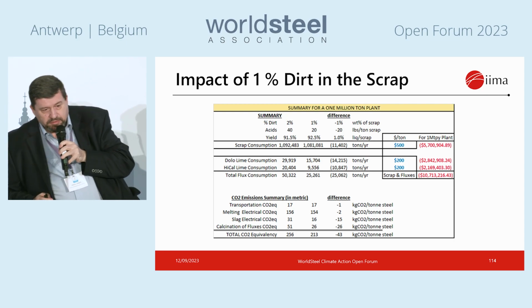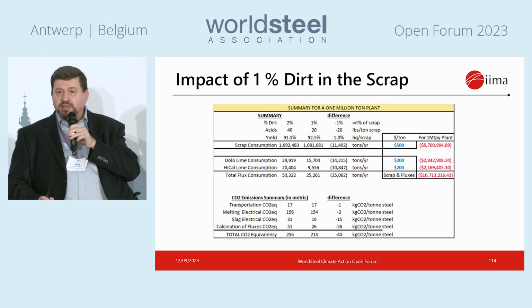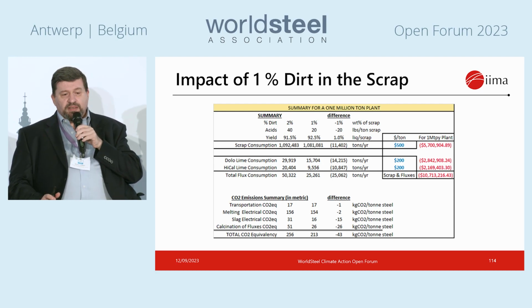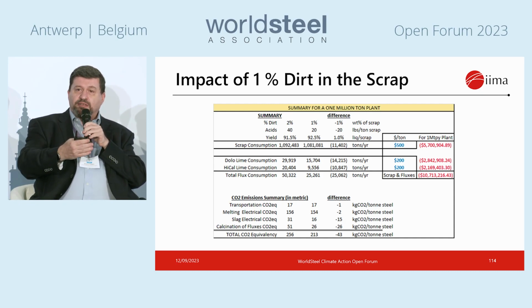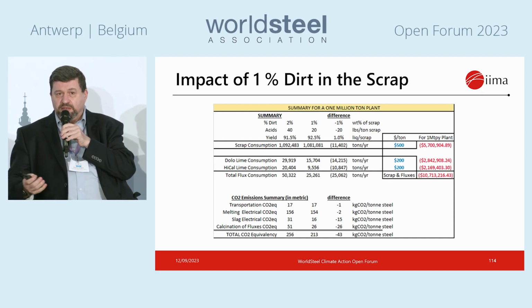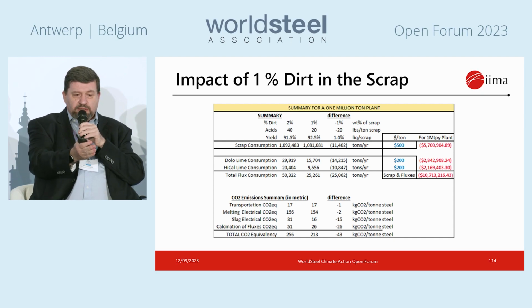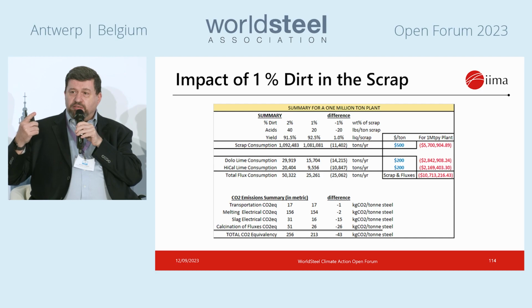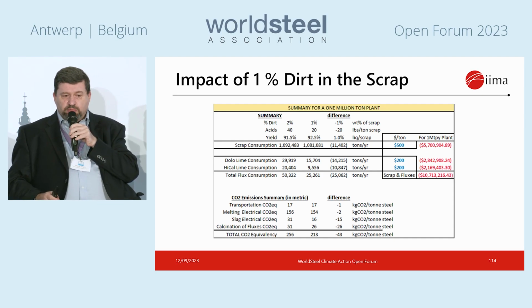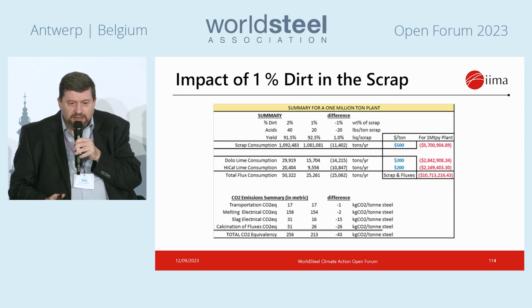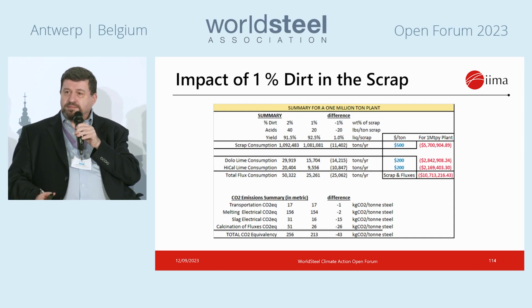Now, just to give you an idea of the impact of 1% dirt in the scrap. So we did a comparison for a 1 million ton a year plant with scrap at 2% dirt and scrap at 1% dirt. These are very, very optimistic numbers. Most people right now are probably dealing with 3 to 4% dirt if they're lucky, okay? So what happens is those represent acid components of the slag. We have to offset those with basic components of the slag by adding fluxes. And the cost to the steel plant, when you look at the increased quantity of slag generated, the extra energy required, the yield losses, this is going to cost this plant, what was it there? Almost $11 million per year. So that's essentially $11 per ton of steel produced.